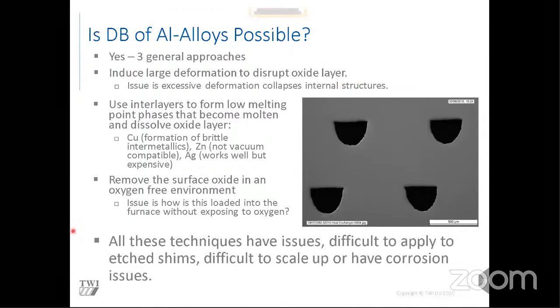The second approach is to use interlayers to form a low melting point phase. Typical materials compatible with aluminium include copper, zinc, and silver, but each has issues. With copper, you can form brittle intermetallic phases. Zinc is not vacuum compatible - all materials have a property called a vapor pressure limit, meaning at a certain temperature in a high vacuum, the material will dissolve from the surface and become a gas. Zinc does that at very low temperatures and low vacuums, so it's not compatible in a vacuum furnace unless you use a partial pressure of inert gas.